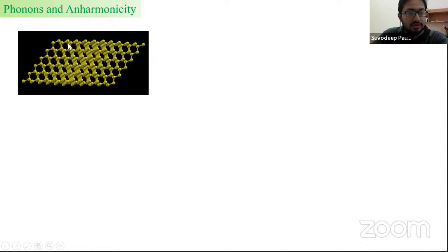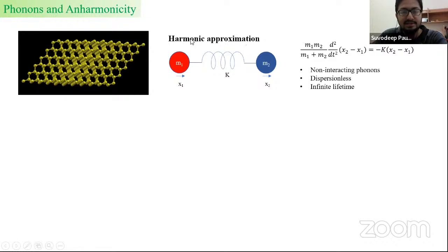So first of all, here we see a lattice vibration, which may be represented by a bosonic hypothetical particle called phonon, and ideally they're considered to be harmonic. And under the harmonic approximation, this is the harmonic equation that we generally represent it with. And under this approximation, we consider the phonons to not interact with each other, and they are ideally dispersionless in energy and have infinite lifetime.